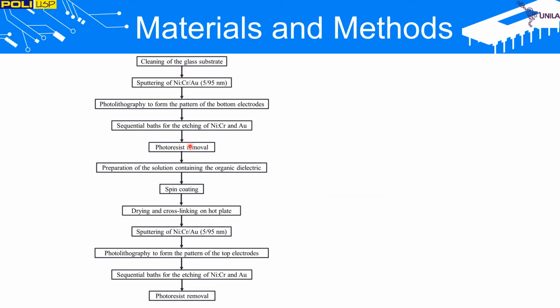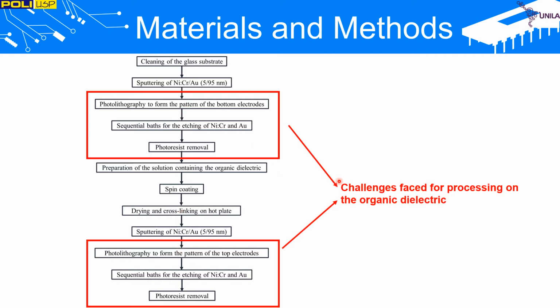In this slide, we can see the sequence of steps to fabricate organic capacitors. Note that in order to obtain functional devices, it was necessary for the dielectric polymer to resist photolithographic processes to pattern the electrodes. In the absence of cross-linking, photolithography of electrodes tends to damage the dielectric film. On the other hand, a higher cross-linking density generates a more defective and consequently porous film. Although a higher surface area is desirable for gas sensing applications, if the leakage current gets too high, an additional insulating layer may be necessary for proper transistor operation.